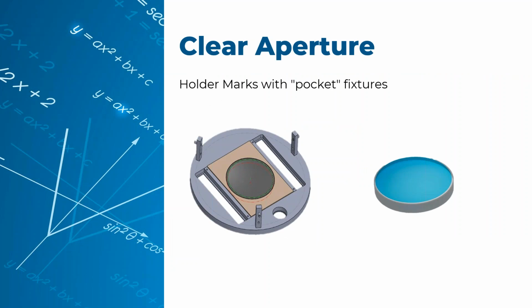Okay, and this is just kind of an idea of some of the different holder marks. So what you have here in gray is an actual coating fixture. Sometimes it's called a pocket fixture or a drop-in fixture. And really what you have is a recessed area with a shelf, and the part will actually drop into the shelf, and the coating will go over the exposed area. And obviously where the shelf is over the optic, that part will be shielded from the coating. And what you'll have is kind of a clean concentric circle all around the outside of the part. So that's typically what, on an easy circular optic, your holder mark will look like.